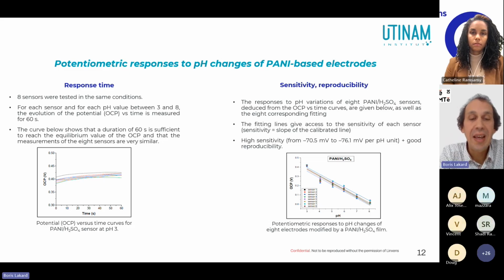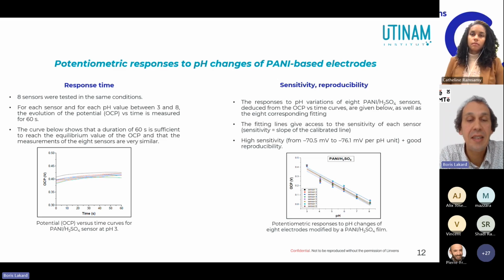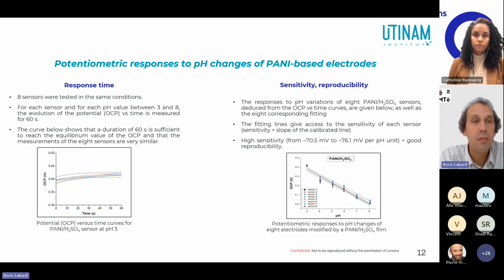The response of 8 different sensors were measured simultaneously. On the left, you have the figure showing that the response of the sensor is reproducible and that the response time of the sensors is less than 1 minute for all the pH values tested between pH 3 and pH 8.